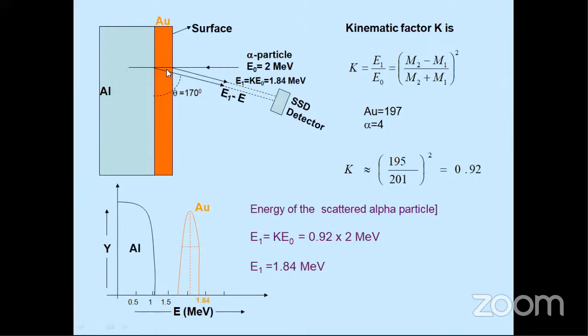Suppose this contains aluminium and gold. So for gold, this is a very heavy element, so the scattered particle will have less loss of energy. And therefore, if you record, the alpha particles scattered from gold will have high energy, but alpha particles scattered from aluminium will have low energy. So you can distinguish the elements in the sample by measuring the energy of the scattered particle.